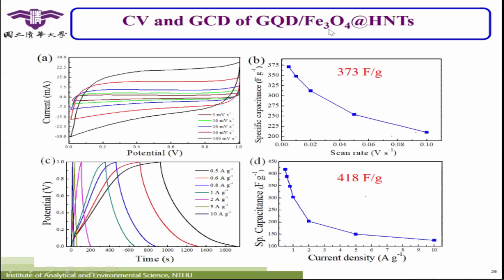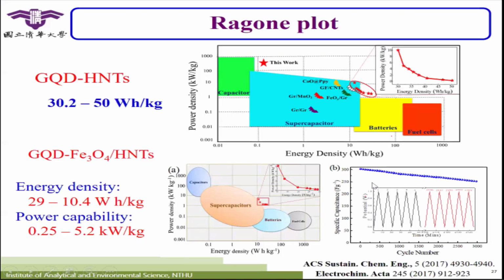If you have the iron oxide inside, the value will increase a little bit because you add some metal oxides, but it may not be good for the energy density and power density. Here is the case for energy density and power density. When we only have the GQD HNT, their power density actually will be high, but their energy density is only around 30 to 50 watt-hours per kilogram. When we add the iron oxide, their energy density decreased a little bit from 29 to 10.4.